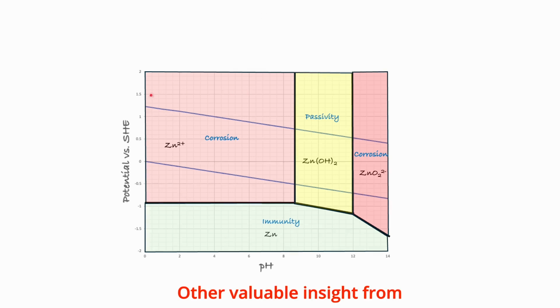Another valuable insight from these diagrams can be obtained by overlapping zinc equilibria lines with the equilibrium lines of hydrogen and oxygen. This overlay allows us to determine which reactions serve as the cathodic processes in conditions that promote corrosion. For instance, with zinc, it is observed that during free corrosion, both the hydrogen evolution reaction and the oxygen reduction reaction are thermodynamically viable, given that the equilibrium line for zinc oxidation is consistently below those corresponding to hydrogen and oxygen reactions.